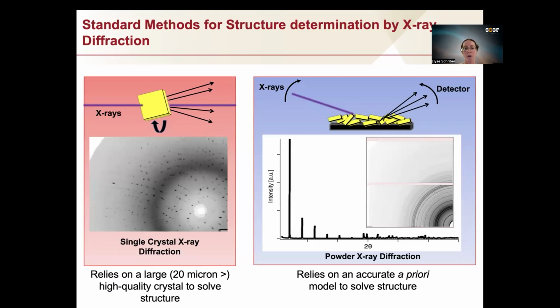The standard method for structure determination by diffraction is simply single crystal X-ray diffraction. You have a large, high-quality single crystal that you rotate through a monochromatic X-ray beam, and what you get is the same thing that we saw in the GIF of the previous slide, where we start to see spots appear and disappear as the crystal is rotated through the X-ray beam. This takes several iterations to collect a complete data set, but is relatively straightforward, and there are actually tools now that make it almost like a pipeline where you don't even have to know what's happening. And what you get out is either some kind of file that you can then analyze, or a complete structure entirely.